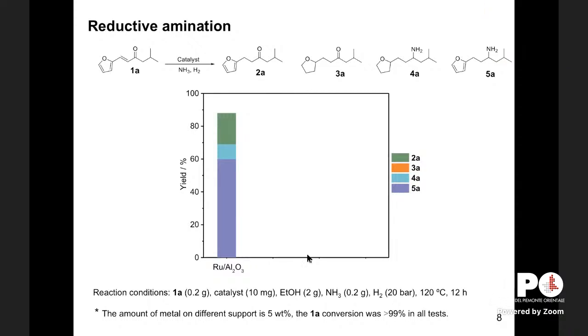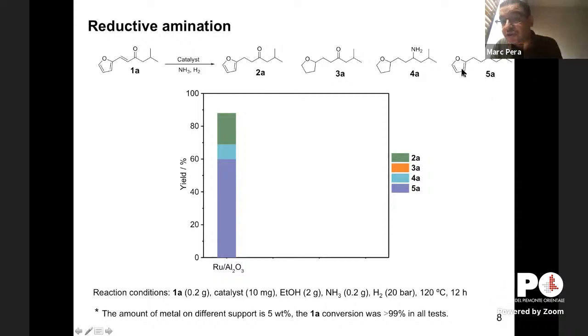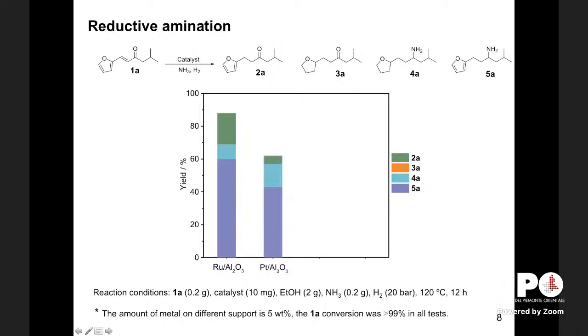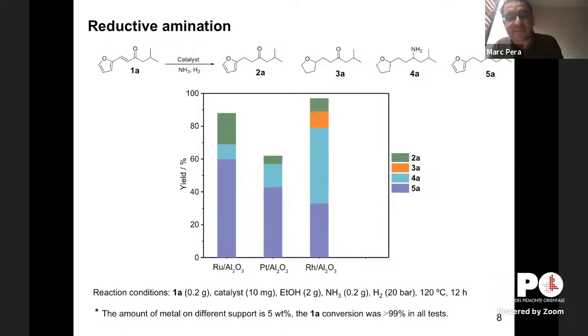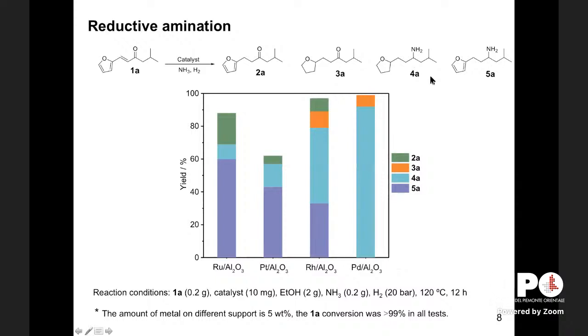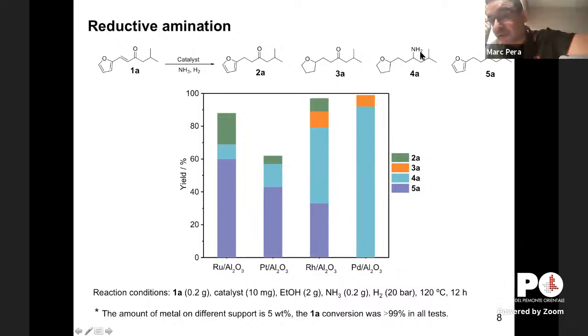So if we use ruthenium, you will form essentially this end product here. So you don't hydrogenate the furan ring. Platinum shows the same behavior, but worse balances. And the best is essentially palladium alumina. That gives us the end product, as I was showing, the most stable product in the thermodynamic analysis.